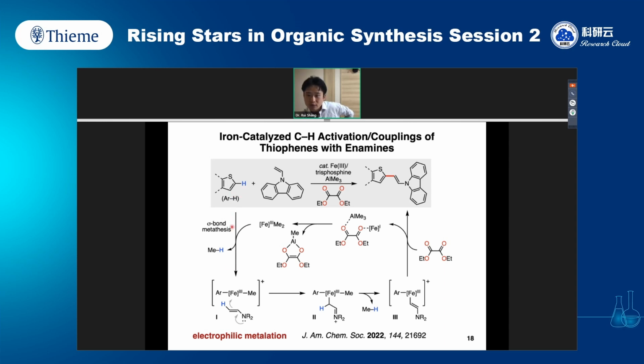The reaction system is similar to the thiophene CH-CH coupling, but the difference is that after the first CH activation, the enamine works as a nucleophile to attack iron-3, and the generated iminium species' alpha CH bond gets easily deprotonated by the methyl anion to generate the alkylated iron intermediate. Then it undergoes reductive elimination to give the product, and the turnover of the iron is similar to our previous case. We use the oxalate and aluminum combination. But this reaction is mechanistically very different from the palladium-catalyzed Fujiwara-Moritani reaction, which is another CH alkylation process.